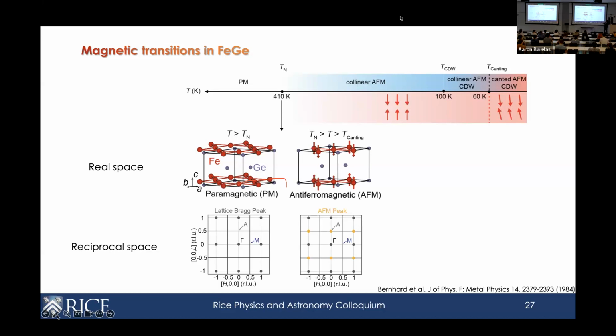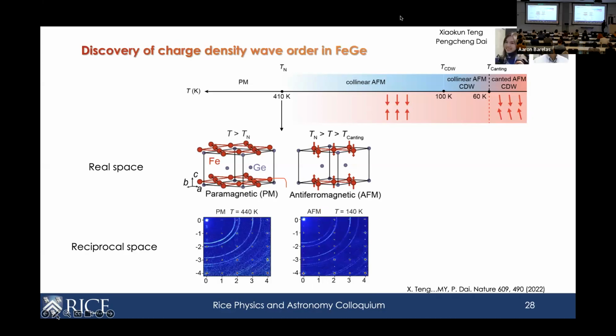So if you think about what you expect, this is real space. In reciprocal space, you can think about the Fourier transform of this, right? What this means is that the unit cell doubles along this axis. So in reciprocal space, if you do diffraction, you would expect to see peaks that appear between the lattice peaks. And so Peng Cheng's group and our shared student Xiaokun did neutron scattering here, and this is exactly what they saw, right? You can see these black peaks from the lattice, and then as you cool down below 410 Kelvin, you can see additional antiferromagnetic diffraction peaks that appear.